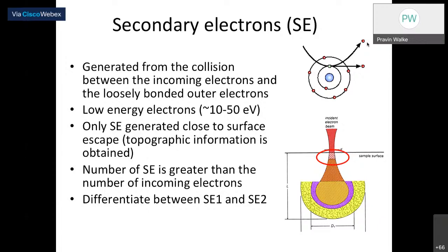Okay, so if we want to have very good topographic information or very nice topographic imaging, then these secondary electrons play a very significant role, right? So what is the number of secondary electrons generated? The total number of secondary electrons generated at the surface is usually more than the number of incoming electrons, right? There are electrons in the outermost orbital as well as the electrons coming from the electron beam, and therefore this secondary electron generation is much more.